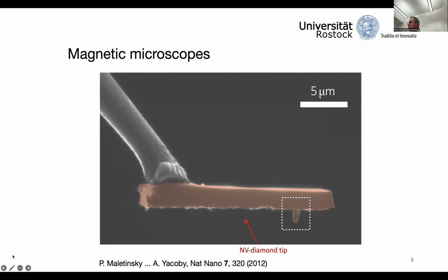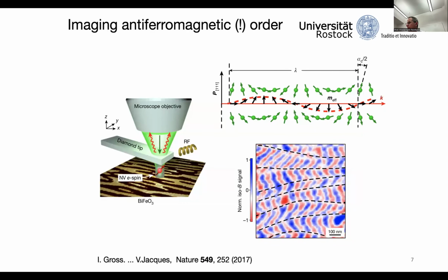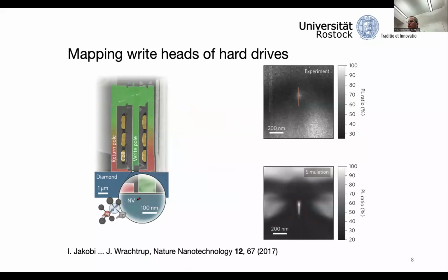People have really managed to make atomic force microscopy tips from diamond. This little brown piece of material is an AFM tip made from diamond. And at the apex of the tip, there is a single NV center in this diamond. And with that, leading labs in the field can obtain images of magnetic nanostructures, for example, of these stripe domains in a special kind of antiferromagnet. This has also been used to characterize the stray field of hard drive write-heads, for example, really close to industrial application.